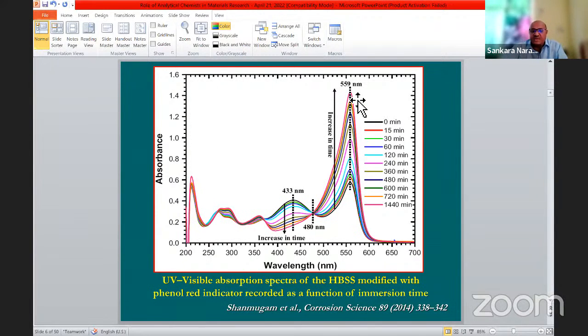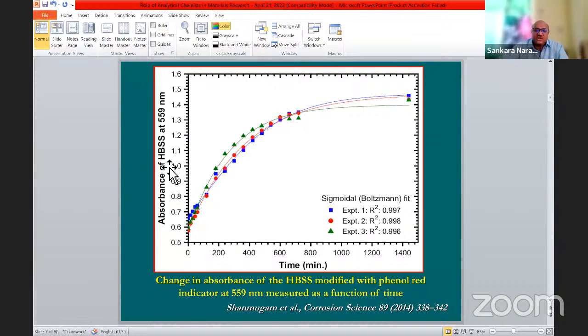This is due to the change in the structure of phenol red due to protonation and deprotonation reactions. So there is a continuous increase in the absorbance at 559 nanometer as a function of time. So we thought that we would measure the absorbance of the solution at 559 nanometer as a function of time, and you plot it. This also follows a sigmoidal fit. The data also follows a sigmoidal fit.